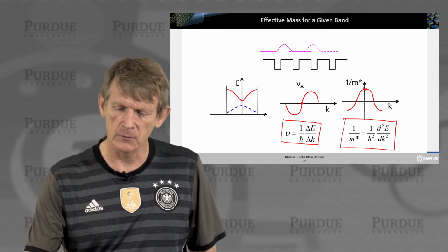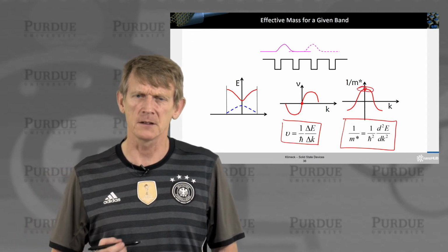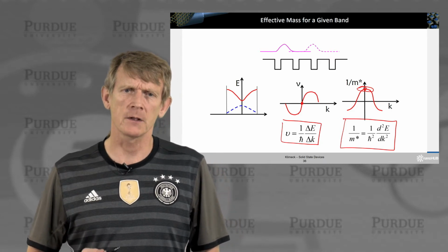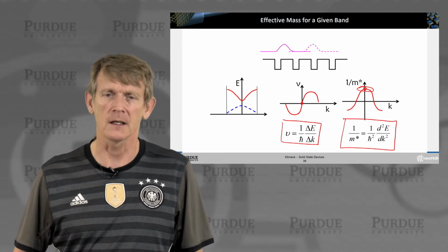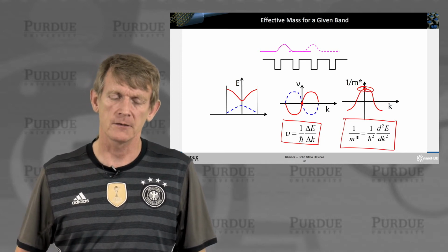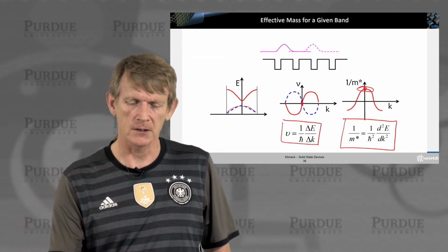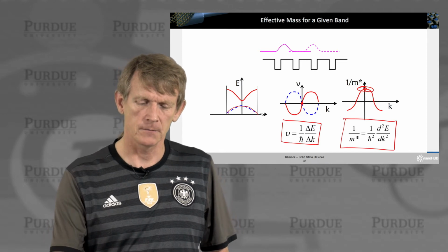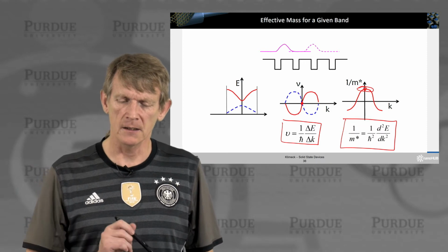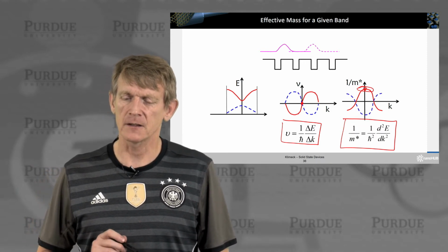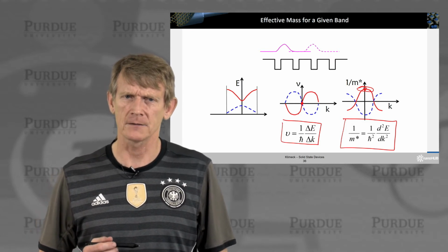We often just deal with energies that are close to here, where the mass is roughly constant in the ideal world, but we'll also explore, especially in nanoelectronics, areas where the effective mass changes significantly as a function of momentum. All right, the other band is bent in the other symmetry direction this way. You compare the blue line here, and you find that the effective mass is actually negative.